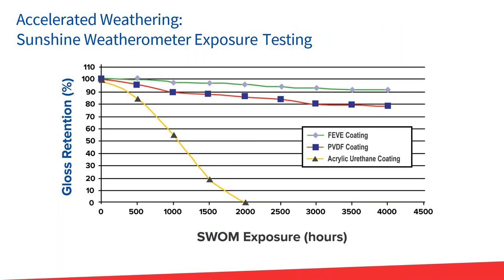And so here you see a comparison of FEVE and PVDF compared to what we would call a conventional polyurethane system. So you're seeing that the fluoropolymers track very well, and you're seeing that not only do the conventional systems degrade, but it's that rate of degrade. And I always say that, you know, with fluoropolymers, it is likely that they will show that kind of extreme rate of decay once they hit enough UV light and exposure time to actually degrade that way. Because again, it's a radical degradation, so it's exponential. But with fluoropolymers, luckily, we just haven't really seen it yet in a lot of our testing.